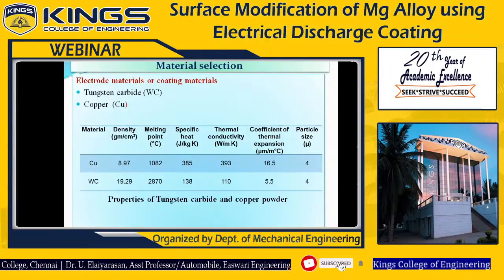So what are the electrodes? There are several electrode materials. In the process, I have chosen 2 electrode materials: one is tungsten carbide, another one is copper. Here we are using tungsten carbide and copper. The properties of the tungsten carbide and copper materials are also given here: density, melting point, specific heat, thermal conductivity, coefficient of thermal expansion, and particle sizes. The tungsten carbide and copper powder particle sizes are 4 microns.